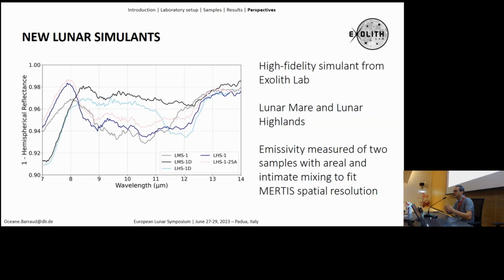So you have to think about an emissivity cup as something like a 5 centimeter wide cup that usually contains powder. But in this case, we have a cup that is split in between. So we have really a thin metal separation. We can do half and half. So it's not an intimate mixture, because it's not what we are going to see on the surface of the moon with MERTIS, but it's a sort of areal mixture, and we're going to experiment with this.